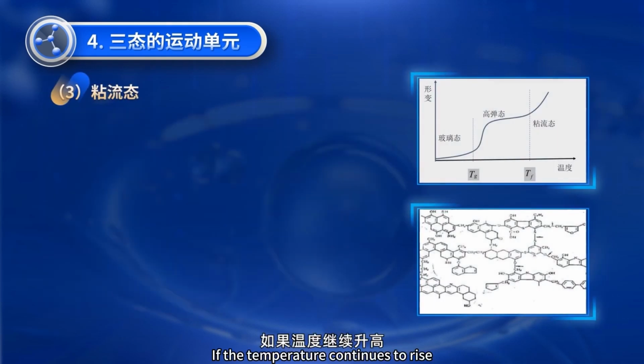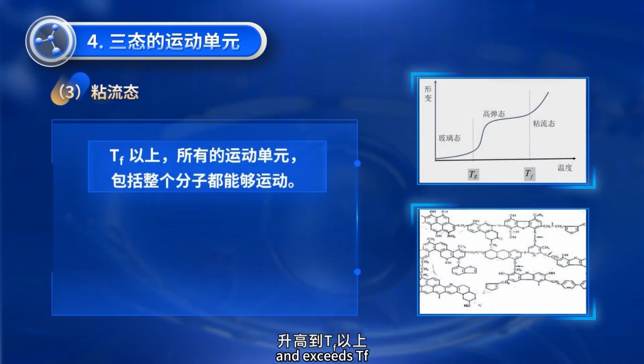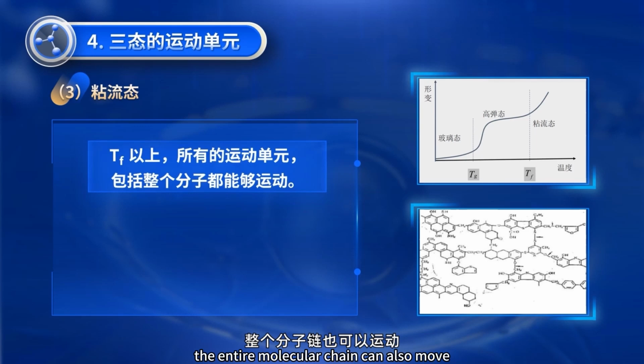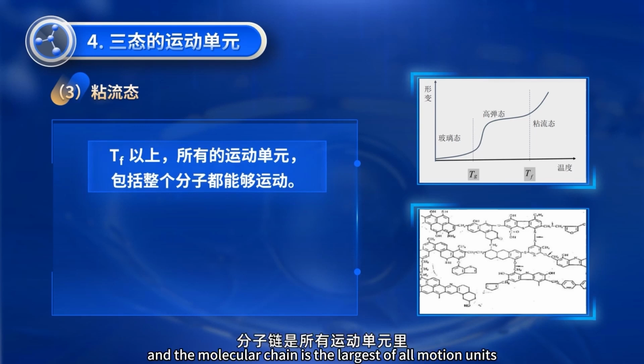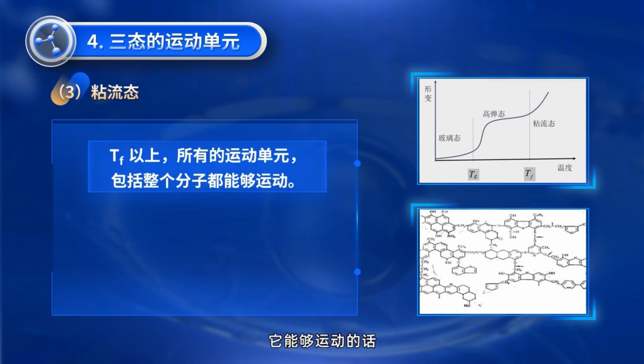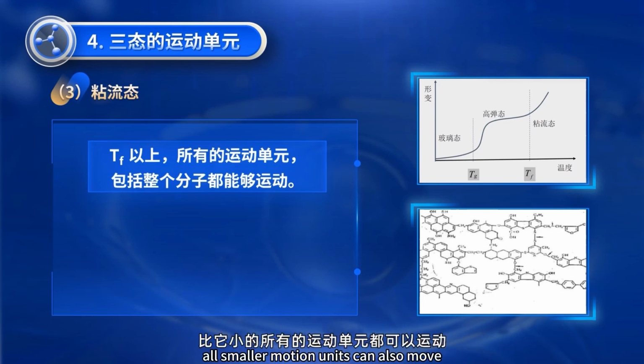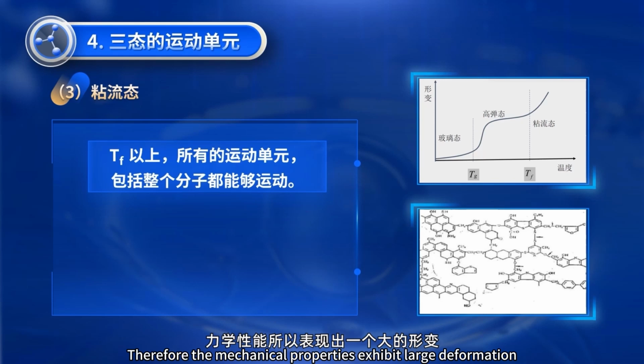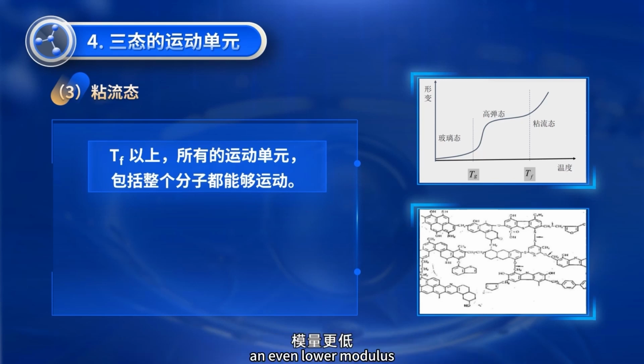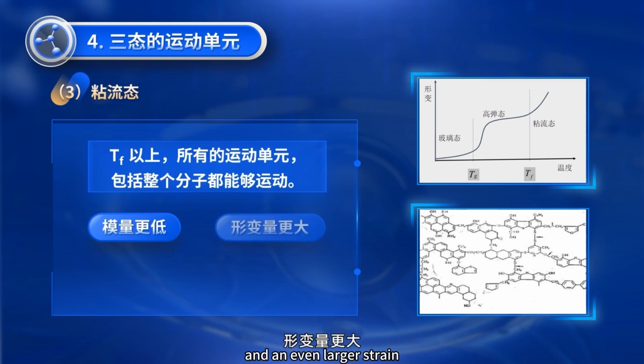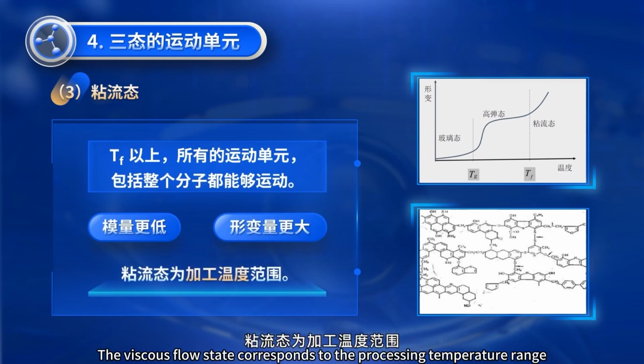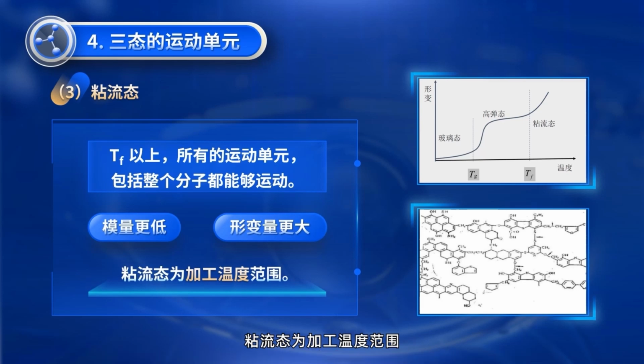If the temperature continues to rise and exceeds Tf, the entire molecular chain can also move, and the molecular chain is the largest of all motion units. When it becomes mobile, all smaller motion units can also move. Therefore, the mechanical properties exhibit large deformation, an even lower modulus, and an even larger strain. The viscous flow state corresponds to the processing temperature range.